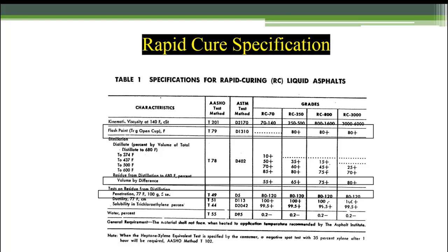So in other words, if that product's out there and it's evaporating, and it's exposed to an ignition source, boom. There were a lot of times, and early on, I didn't see it in person, but I've heard stories from valid sources that the poor distributor person would get up early in the morning, go out, and start heating up the tank to shoot RC. Next thing, if they're standing next to the truck, the thing explodes. Why? Certain humidity conditions and vaporization. Once it's in the tank, the solvent, in this case the gasoline naphtha, is going to start evaporating off, come out of the tank and circulate in and under the tank. Guess where you light the flames? Under the tank on the distributor truck, and boom. So that's the safety part of the issue with RCs.